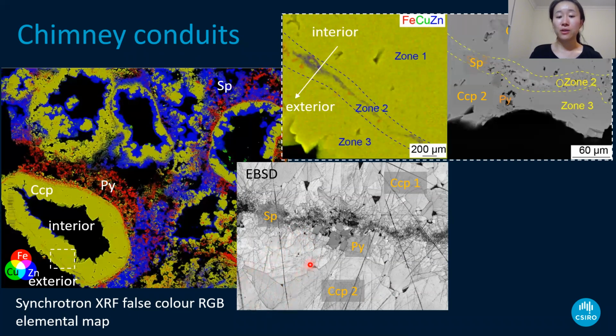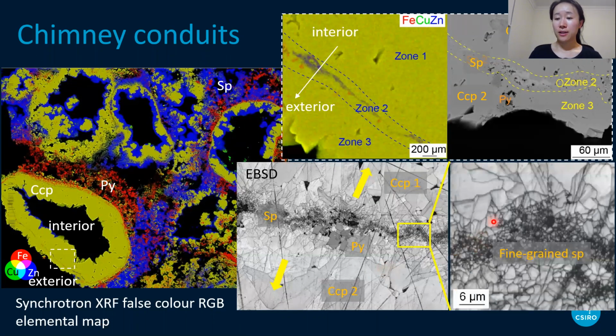So you can see these are crystals. This whole image shows the distribution of the microcrystals of all the sulfides. Here we can see actually the chalcopyrite grows in two directions, interior and exterior respectively. If we zoom in on the sphalerite layer area, we can see actually it contains a lot of fine-grained particles.